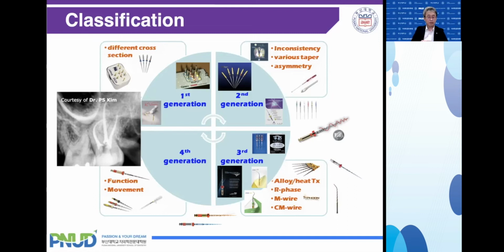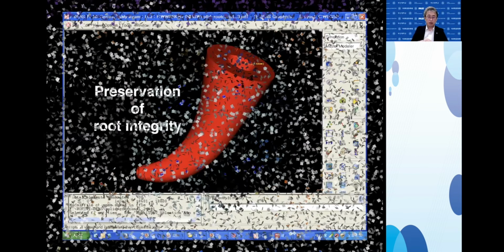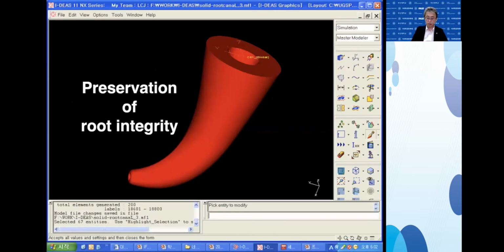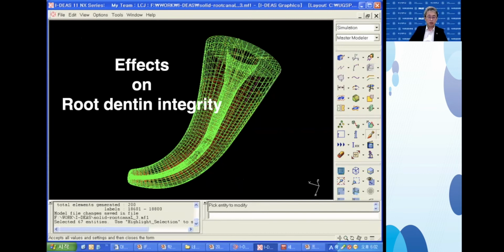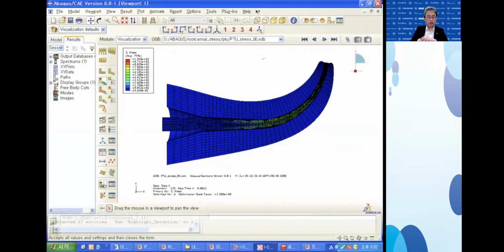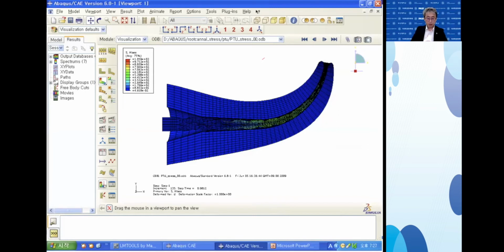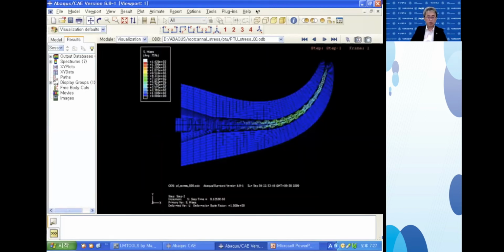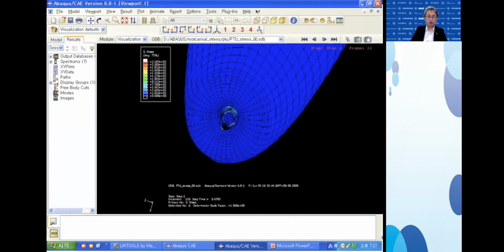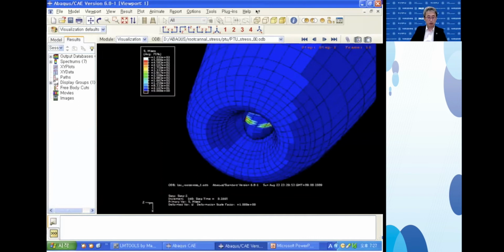The root dentin integrity is directly related with the endodontic prognosis. So we did a finite element analysis study. This is the root finite element model, and inside of this model, we have rotated the finite element file models. You can see the simulation motion. The file rotated inside of the root canal. We could calculate the stress generation and the stress value, not only for the nickel titanium instrument, but also for the root dentin near the apical foramen. You can see the color change. Red color means very high stress generation.